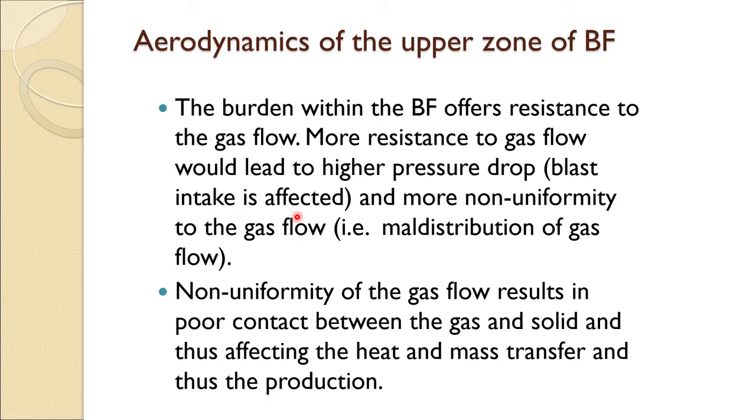The blast intake, which you are putting from the bottom, and your pump capacity, everything is going to get affected, and thus the non-uniformity of gas flow, or the maldistribution of gas flow as we call it, will occur in the region. Non-uniformity of the gas flow results in poor contact between the gas and solid, and thus affects the heat and mass transfer and thus the production.